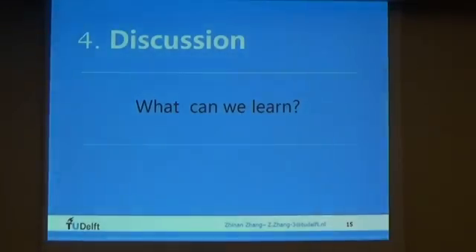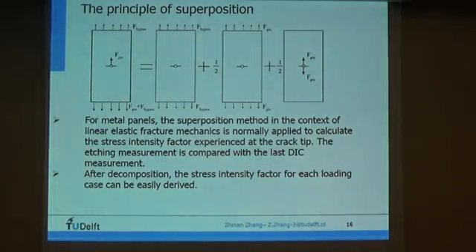That's the result. So what can we learn from this result? Just as we know, for the metal panel, the superposition method in the context of linear elastic fracture mechanics is normally applied to calculate the stress intensity factor experienced at the crack tip. After decomposition, the stress intensity factor for each loading can be easily derived. For example, this is a load case. We can decompose it, and for each of these load cases, we can calculate the stress intensity factor easily.